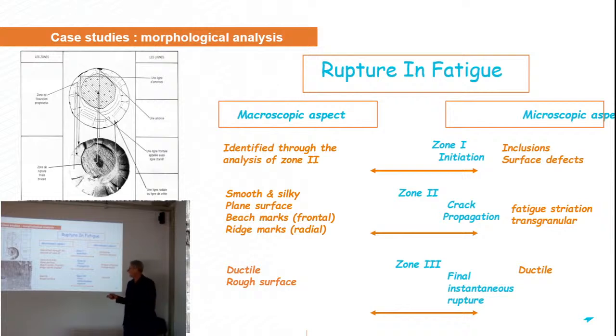Okay? So, on this part, which is the zone where the crack propagates after its initiation on the defect, you can see beach marks, frontal marks, and ridge marks, which are radial marks. Okay? And if you go here to the final fracture, you have a fracture which is ductile and you have a rough surface.